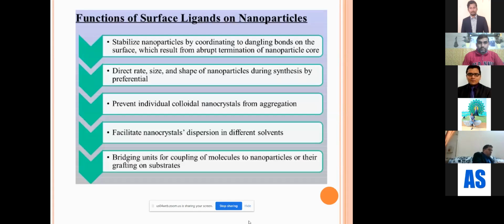So functionalization of the surface ligand of the nanoparticle is one of the important parameters, where you want to stabilize these nanoparticles by not disturbing the core of the particle. You want the functionalization so that you can continuously get the exact shape and size of the nanoparticle. Proper functionalization is very important, and you want to prevent aggregation or agglomeration, where you want these nanoparticles to be in the colloidal nanostructural feature to hold this feature.